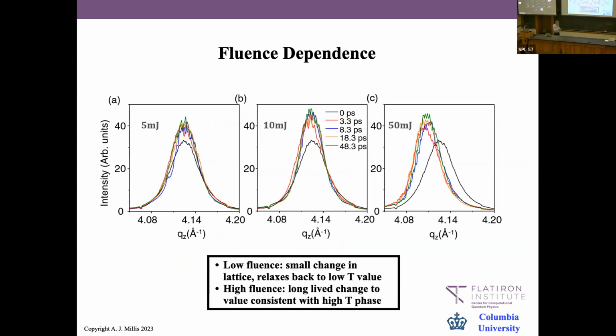Okay, this is what I said before: basically, if you hit it very lightly, nothing much happens, except for an increase in scattering intensity, which I'll tell you about more later. You hit it hard, and the peak position shifts.